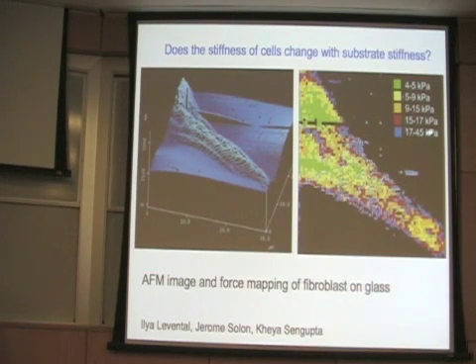So some parts of the cell look like there are a few tens of kilopascals. Some parts, more in the interior of this protrusion, are about 4 kilopascals. It's relatively heterogeneous, and the upper limit seems to be someplace around 20 kilopascals, for example, for this cell type, sitting on something that's infinitely stiff, that's gigapascal. And this is just the tip of the cell. The nucleus is way back somewhere else.